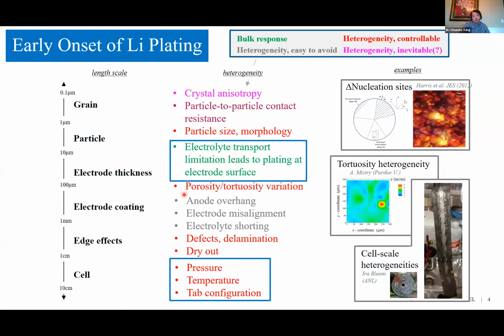Lithium plating is the formation of metallic lithium around the anode of a lithium battery during charging. It causes lithium battery to fail over time. Plating is usually associated with heterogeneity. Heterogeneity leads to inhomogeneous distribution of lithium, resulting in stress that may cause plating. Heterogeneity can occur at a wide scale from micrometer particle up to the cell level. Some heterogeneity is a bulk response, such as electrolyte, due to its transport limitation. Some heterogeneity can be manageable, such as pressure, temperature, and the tab configuration for a battery cell.